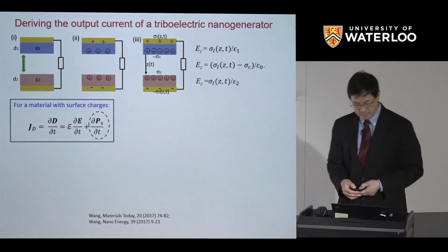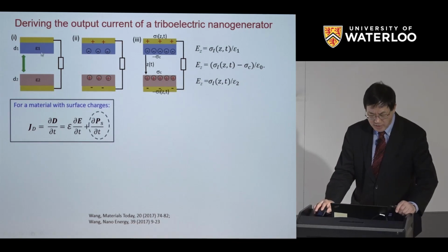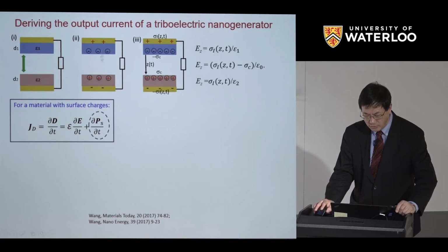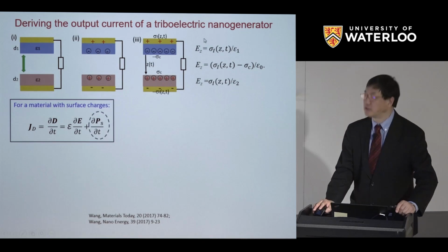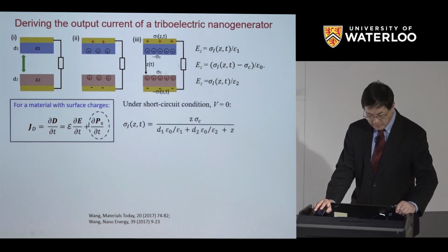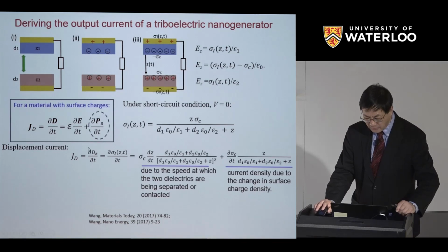Let's go to theory. Displacement current. So we have two dielectrics, and here's the gap. If we make physical contact, we deliver electrostatic charge from one to the other. And if we make more contact, even more charge. So for these three zones here, you can work out the electrostatics, and you can calculate the displacement current due to the surface polarization density. Surface polarization means the polarization due to the presence of this electrostatic charge. You can derive that the displacement current has two terms.